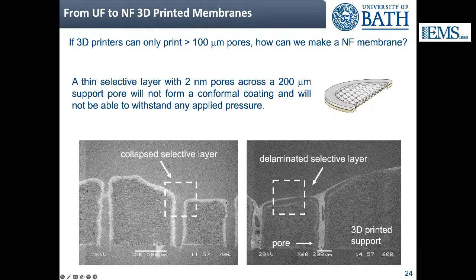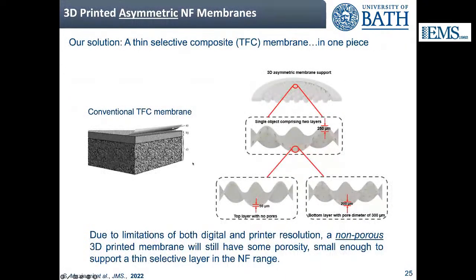What you see here is a cross-section of a 3D printed membrane. This part here is the 3D printed support. This brighter area is the PVDF nanofiltration layer. You can see that the layer has broken down and collapsed into the pores of the membrane. Or if it doesn't break down, it delaminates, as you can see here. This is the support, this is the pore of the support, and this is the layer. So we had to think of a different approach to make nanofiltration membranes using this technology.